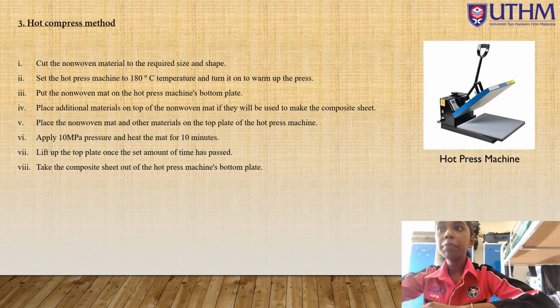Later, place the non-woven mat and other materials on the top plate of the hot press machine. After that, apply 10 megapascal pressure and heat the mat for 10 minutes. Later, lift up the top plate once the set amount of time has passed. Finally, take the composite sheet out of the hot press machine's bottom plate.